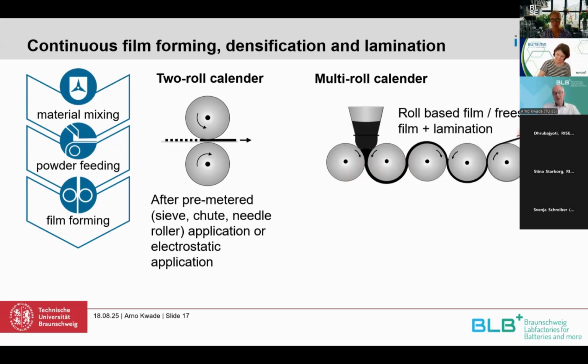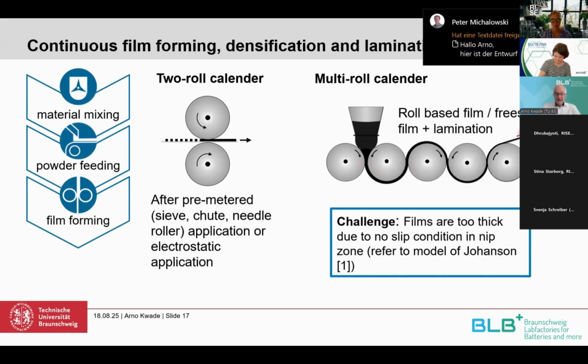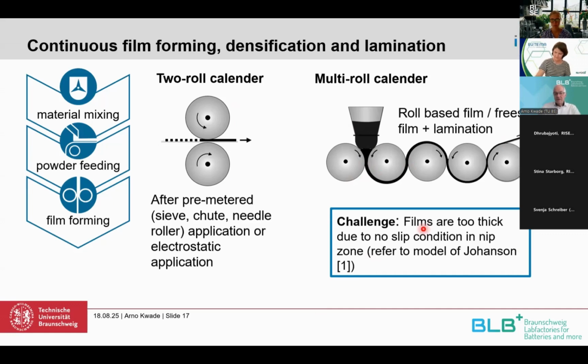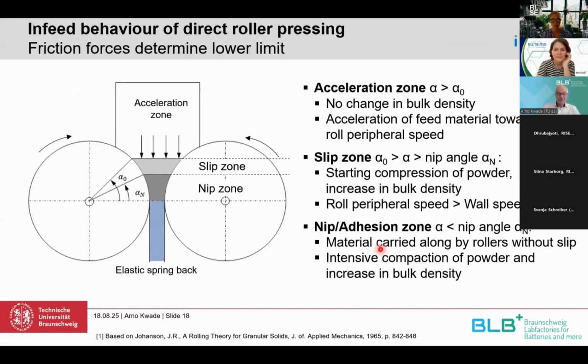The question is how we can get the right film thickness, as the films are too thick due to the no-slip condition. If we look at the theory, there is a model of Johanson. I wanted to show it to you very shortly, so you see that there is already some very old literature on normal roller granulation available. And you see that there's this acceleration zone, then we have the slip zone.